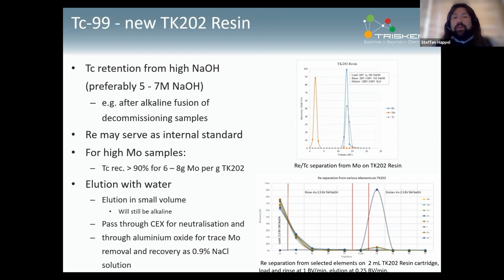And if you still want to increase your detection limits, or have a much smaller volume for your measurement, you can then take the solution, still go through an aluminum oxide cartridge, concentrate the technetium, and then elute in a very small amount of sodium chloride to get a solution that is again highly concentrated compared to what you have in the beginning of the separation.